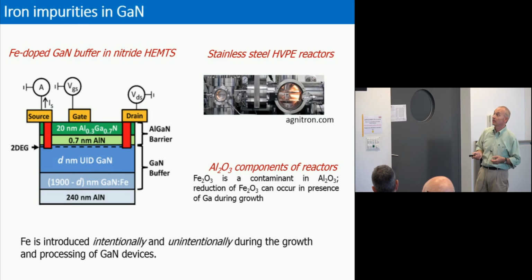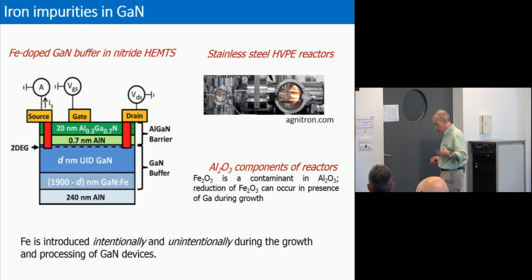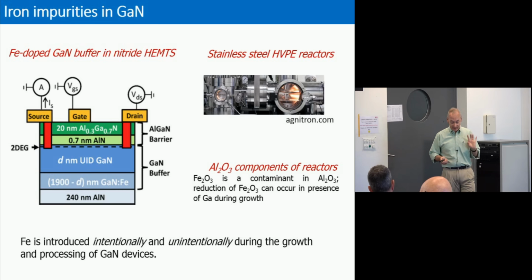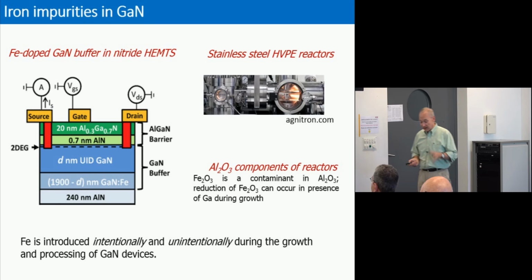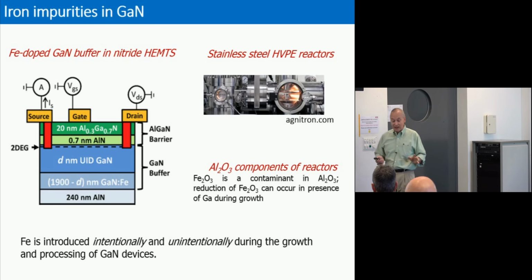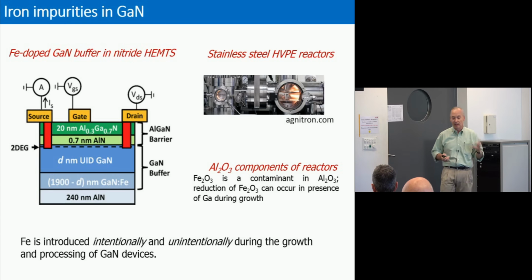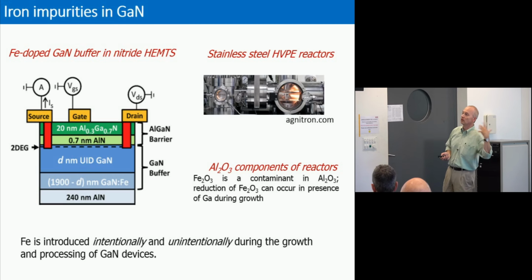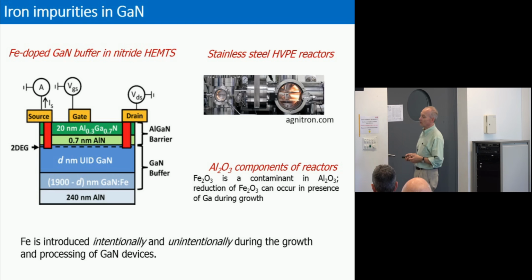For those of you who may not be familiar with silicon technology, transition metal impurities are known as killer centers. If you have any transition metals present in your silicon, even though that's not for light emission, but even for transistor operation, they're going to lead to very high rates of non-radiative recombination. Transition metals are known to be really bad.